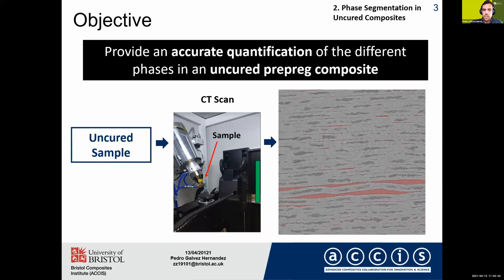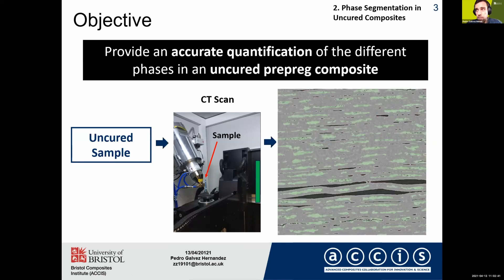This technique provides nice results for voids, but it still misses a lot of really small voids, and it really fails in segmenting dry areas. As we can see in the right-hand image, applying a threshold to the grayscale image produces a lot of false positives and false negatives. It doesn't capture the dry areas in a faithful form, so it doesn't provide an accurate representation of what we are looking for.